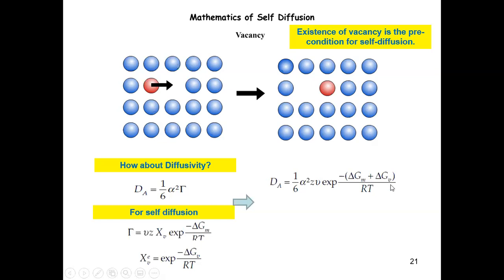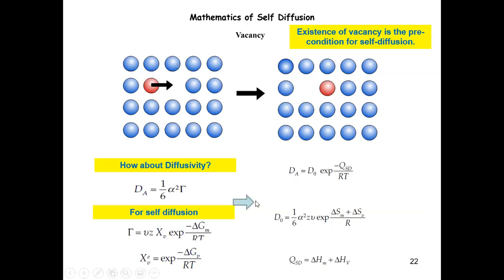Okay, now this is another way of looking at this: diffusivity for substitutional diffusion is much smaller than for interstitial, because the energy barrier is increased a lot, since we have to consider the creation of a vacancy as well. Once we understand that, I think this is pretty straightforward. We can also write down the contribution to the free energy difference by creating a vacancy in terms of entropy contribution versus enthalpy contribution, etc. And eventually you can still write down the diffusivity in this particular form, right?